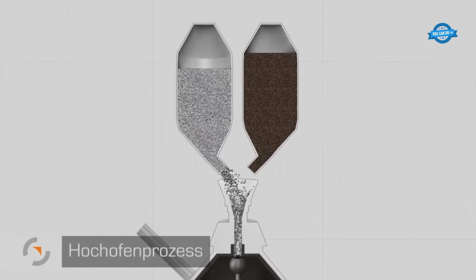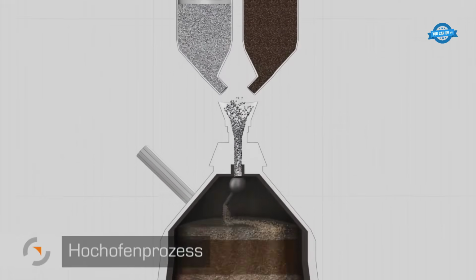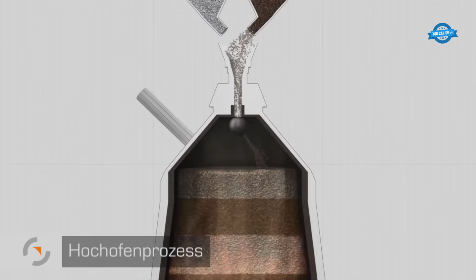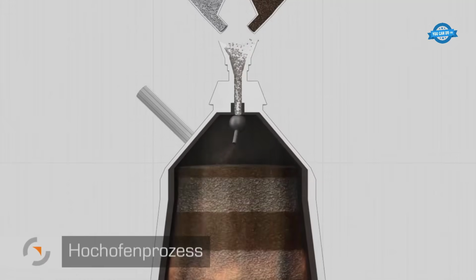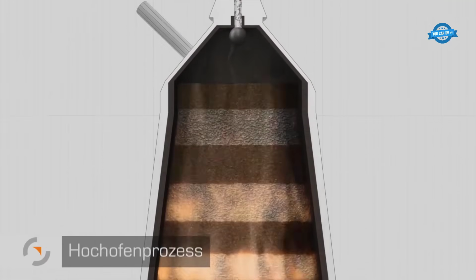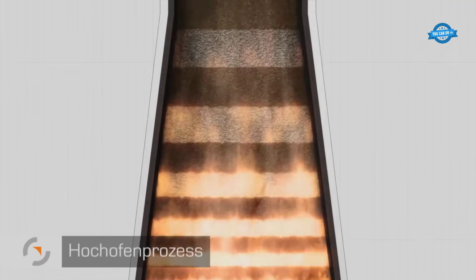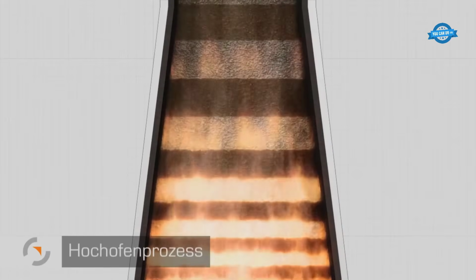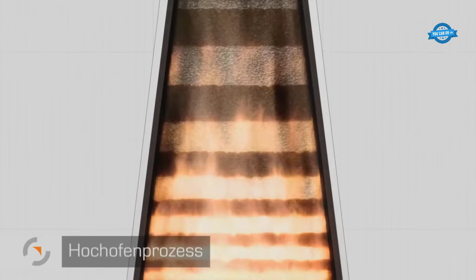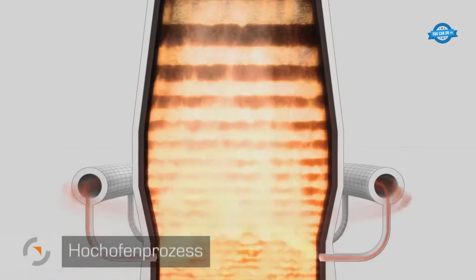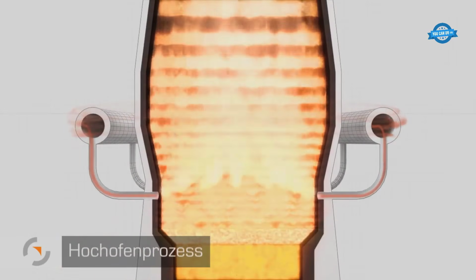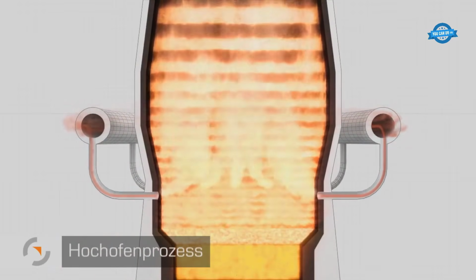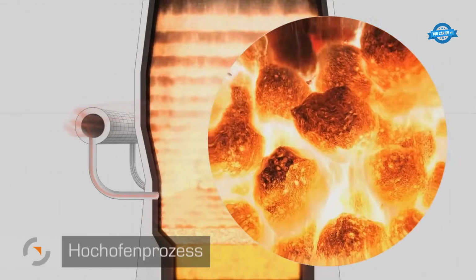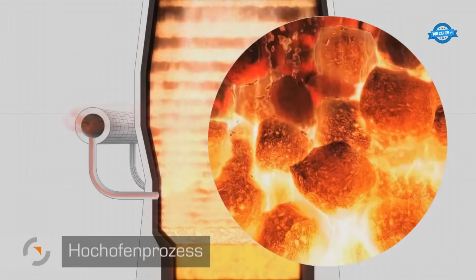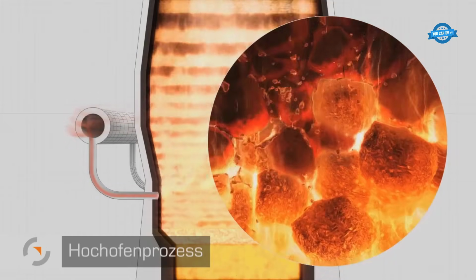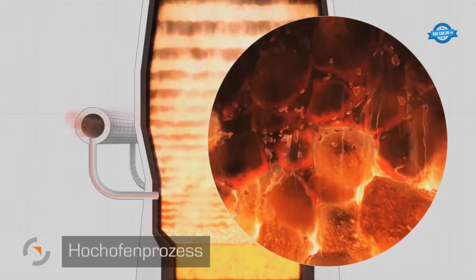chute. As the layers descend, rising processed gas, generated by preheated air at 1,200 degrees Celsius, initiates the reduction and melting of iron ore. This arduous process, taking 8 hours, culminates in liquid iron and slag in the lower part of the furnace, with periodic tapping every 2 hours. At around 1,450 degrees Celsius, the pig iron and slag are forcibly discharged through the tap hole and immediately separated.